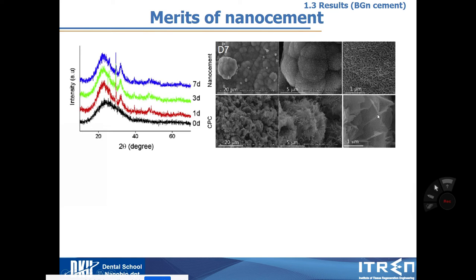When you look at this, this one also shows hydroxyapatite crystal, but this crystal is larger than this nano cement. So we can say that when you look at some cell, the cell size is around 10 to 20 micrometer. So when a cell wants to touch their microenvironment, their size is less than micrometer, like 100 nanometer or a few nanometer. So you can see that compared to this micro-sized crystal, this nano-sized hydroxyapatite crystal is better for stem cell differentiation or stem cell touching.